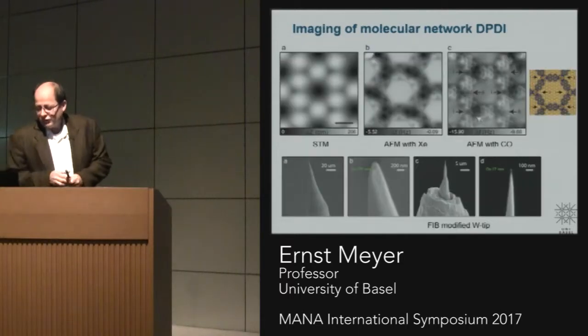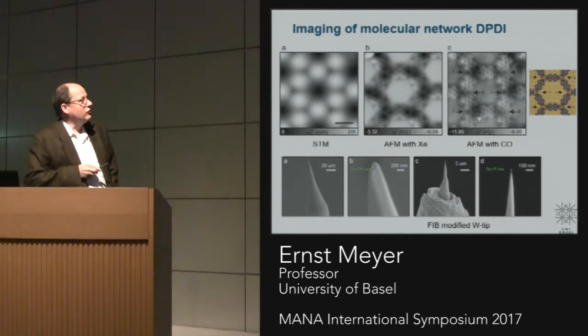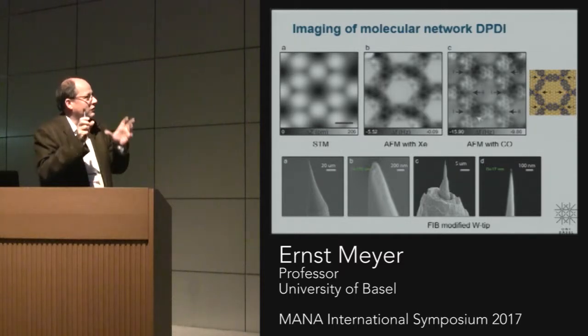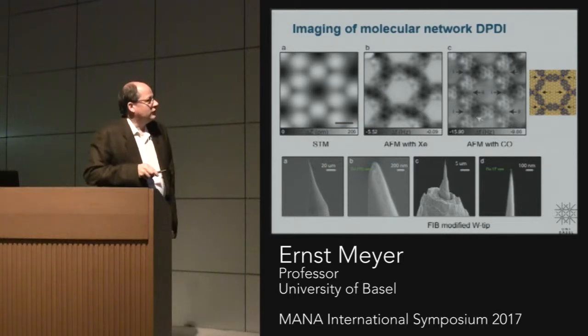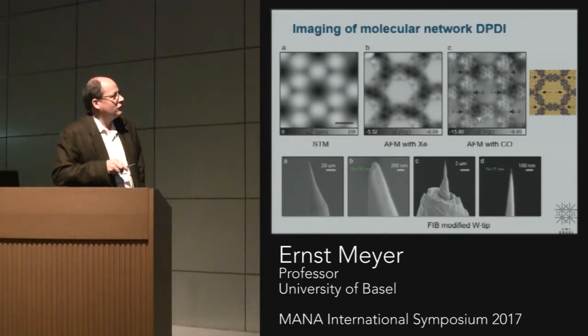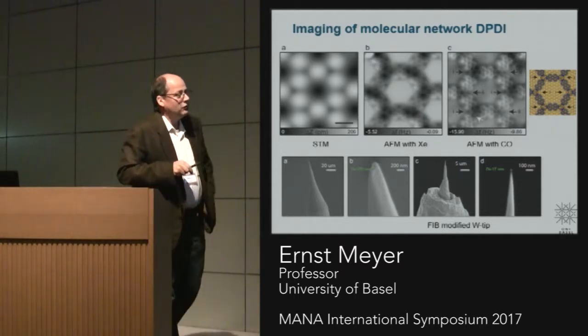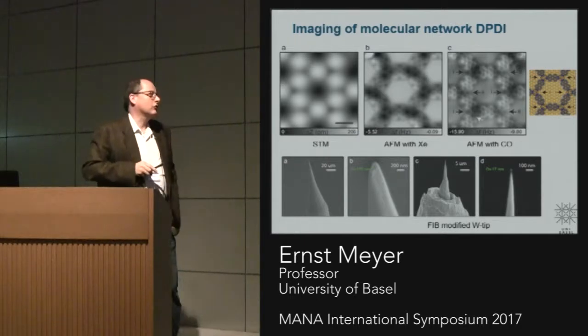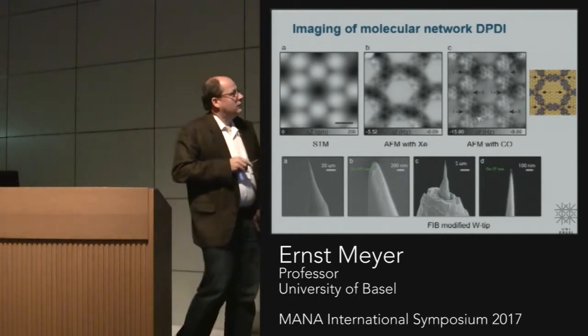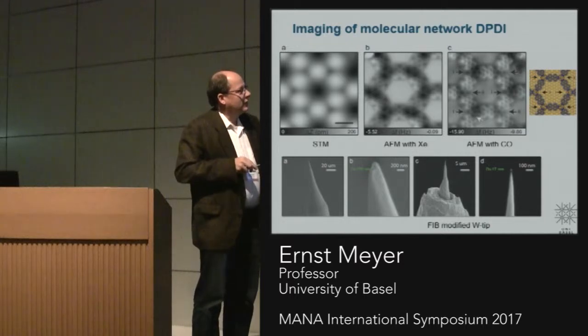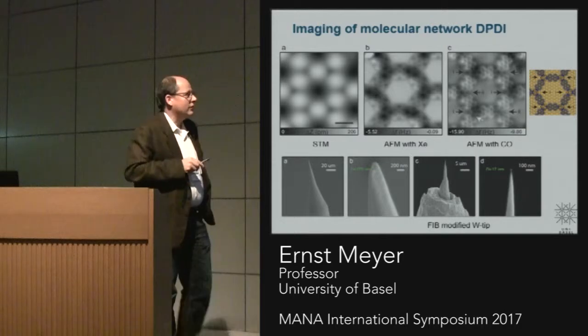And I just wanted to show you again the flavor of STM compared with AFM. So this is the STM picture. You more or less just see where the molecules are. If you use a xenon tip, you can already sort of see what it probably is. If you use a CO tip, it's even better because you can get even a bit closer. It's a bit more stable than the xenon, and then you can basically identify the different locations of the molecule and really identify what you have.